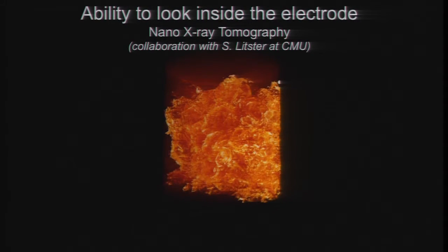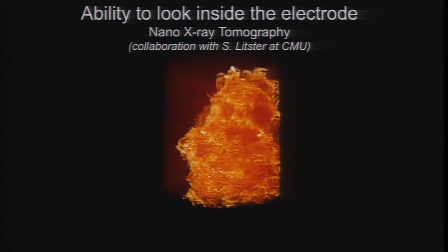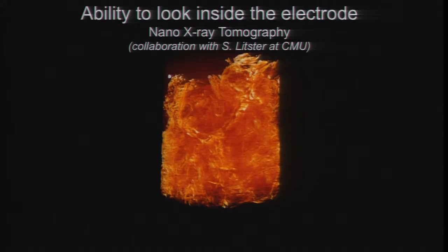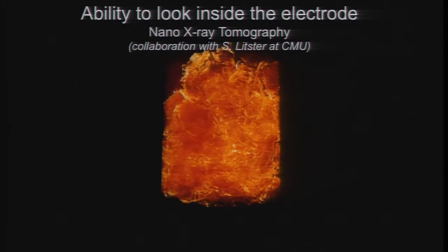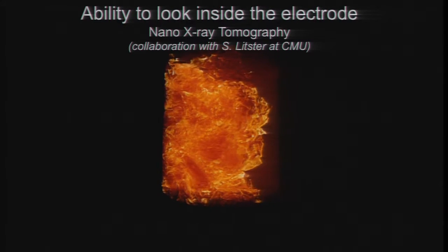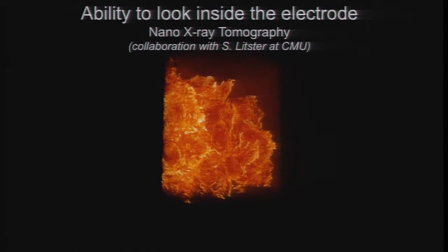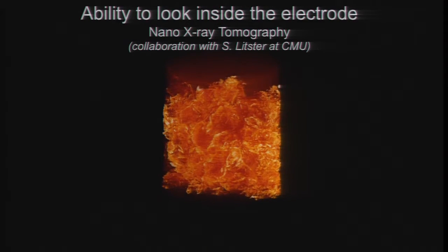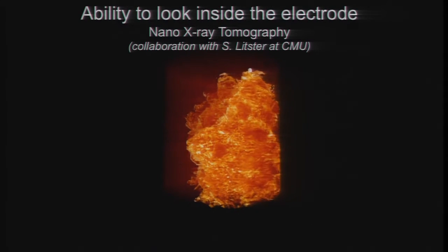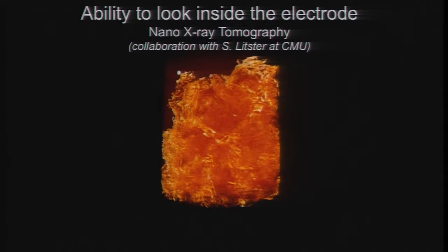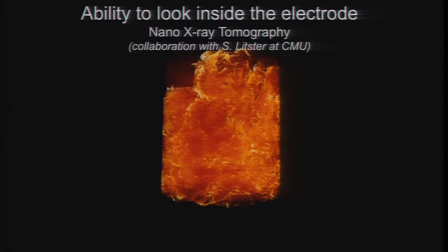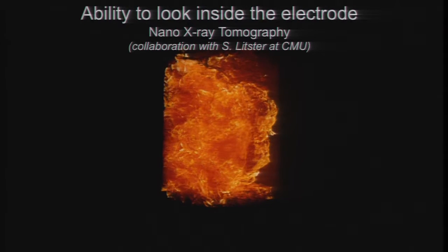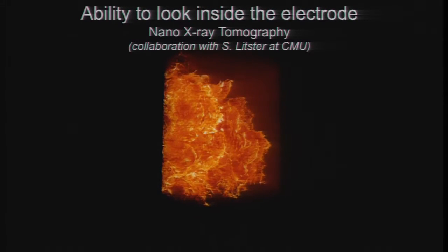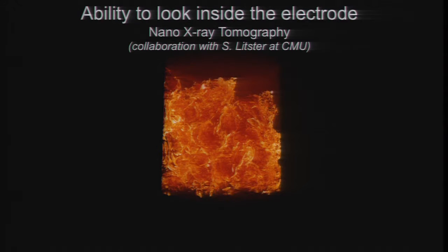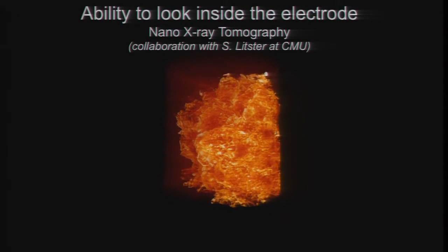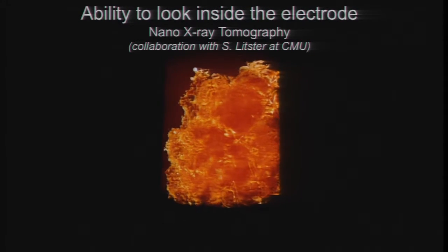But we have another way to look at this, and this actually is in collaboration with Sean Lister and his research group. This is a nano X-ray tomography image, and it's a three-dimensional rendering where you can use the same kind of X-ray CT that you might be familiar with from a medical perspective. You can do it with nano resolution on these very lightweight electrodes. This is a carbon system, so it's very difficult to get this resolution and this imagery correctly. This is actually an extraordinary image. We can see all these different graphitic flakes in here. You can see a tremendous amount of detail, and these white dots are really representative of buildups of some sort or another.